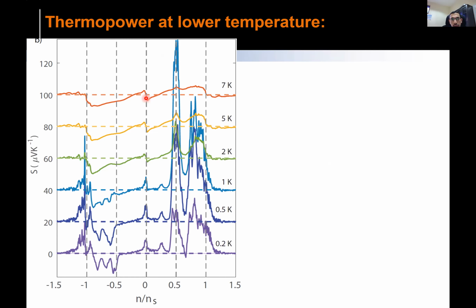So here from this Dirac point to this one, you need 4 electrons. Similarly, from this Dirac point to the valence band also 4 electrons. So total 8 electrons are required to move from this point to the other point. So I'm calling this plus 4 and this minus 4. That's the conventional nomenclature to be used. And this point particularly, which I'm calling half filling, is nothing but 2 electrons per Moiré cell. It's happening at 7 Kelvin. You see there is a small hump coming.